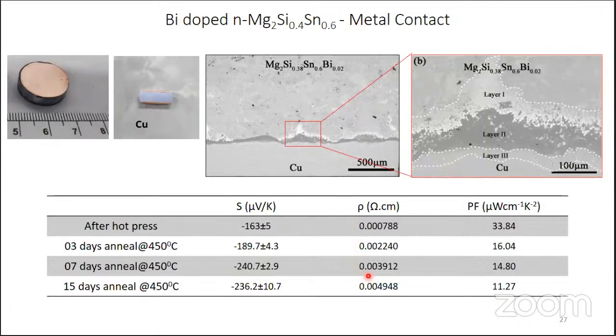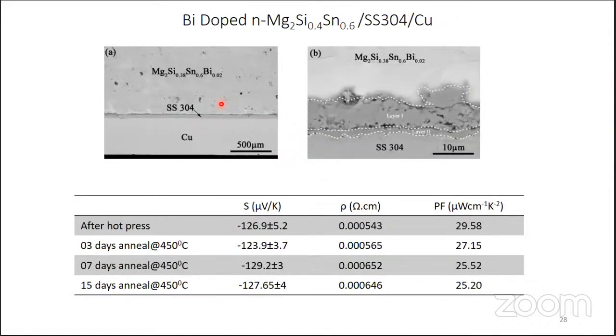Effectively, it's a disaster. As prepared, this is the resistance and Seebeck coefficient. After 15 days of annealing, you end up with completely different parameters. So if you try to make a module by directly bonding this thermoelectric material with the electrode, it's not going to work. It will not be thermochemically stable. So for this one, we tried a different material, and finally we froze on stainless steel SS304 as the barrier layer.